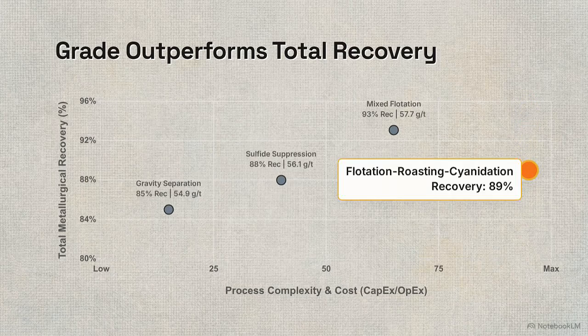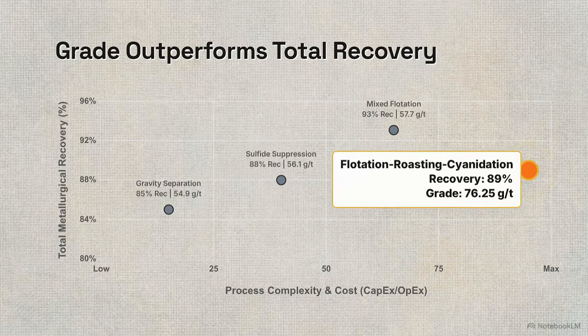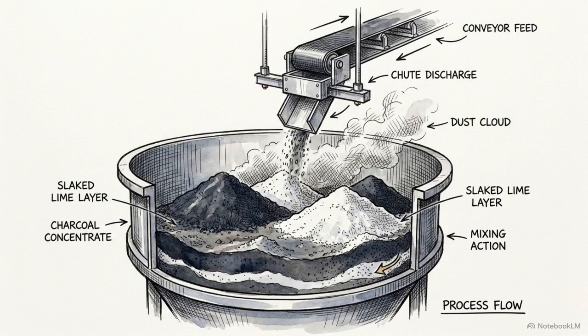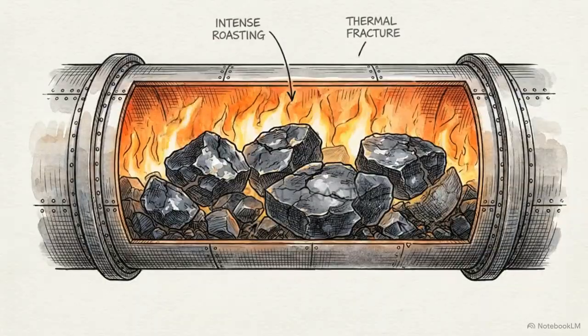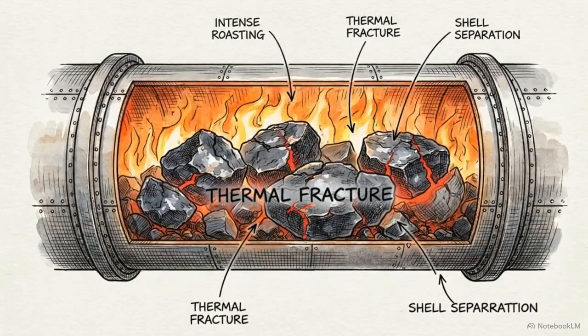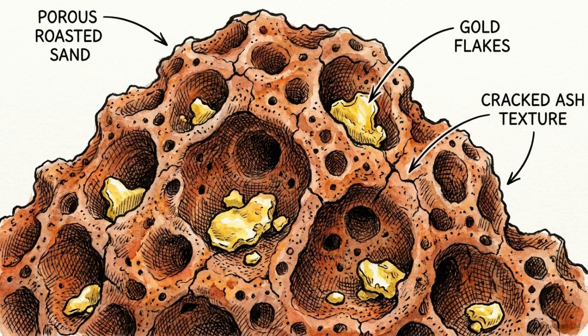At the extreme far right, Flotation Roasting Cyanidation sees total recovery drop slightly to 89%, but the grade jumps to 76.25 grams per ton. The process begins by enriching the ore via flotation, then mixing that concentrate with slaked lime and specific additives. The mixture is heated to 650 degrees Celsius, a process which completely destroys the rigid sulfide structures that encase the gold. This creates a highly porous roasted sand, with the gold particles finally exposed for extraction. The roasted sand is then mixed at a specific solid-liquid ratio and leached with cyanide.